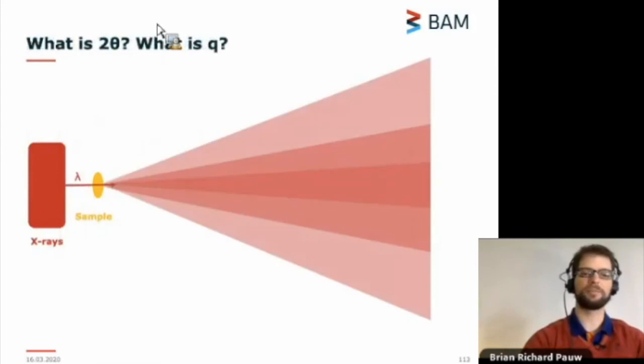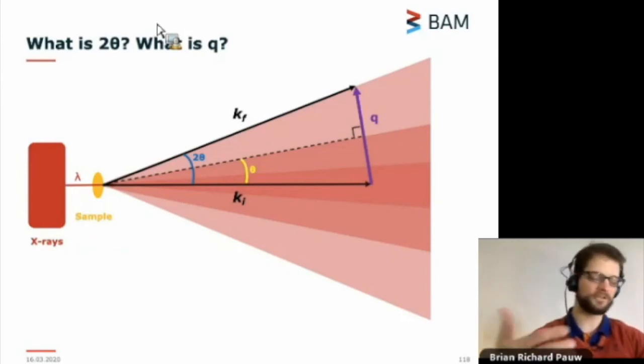So to put that graphically, for X-ray diffraction, your angle 2 theta is simply the angle between the diffracted beam and the beam that goes straight. For Q, we've normalized this by the wavelength of the radiation that we use. But why do we do this? It's not just to make this conversion to d-spacing easier. It has additional benefits. And the benefits come when we measure samples with different energies.